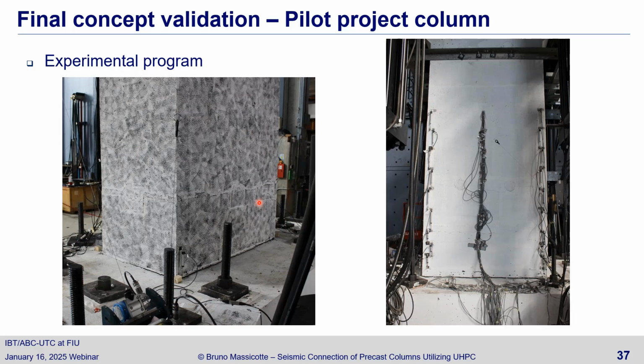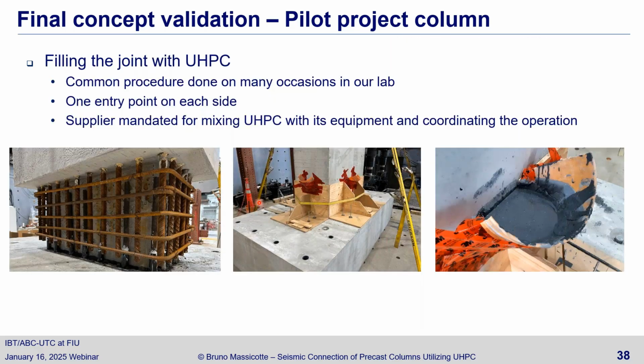So did it go well? Because it's UHPC, and so filling the joint, we've done a lot of UHPC mixing in our lab for many columns, many big projects, and so in that case you can see the detail. This is the void that has to be filled, and we had 4 entry points here, so that you can put UHPC on one side and then it flows to the next side, so you can make sure that you fill it up to the top.